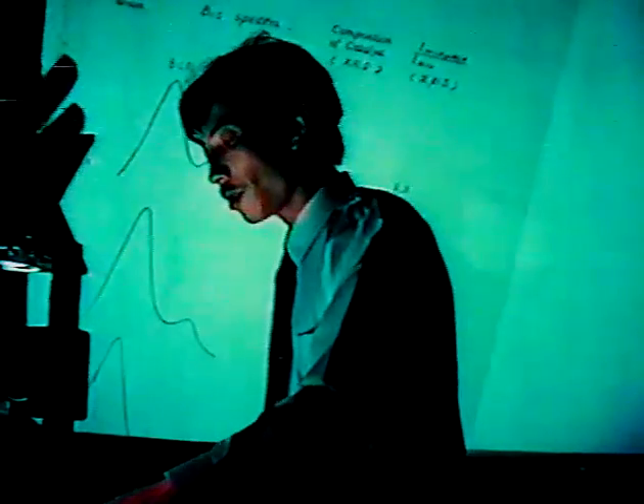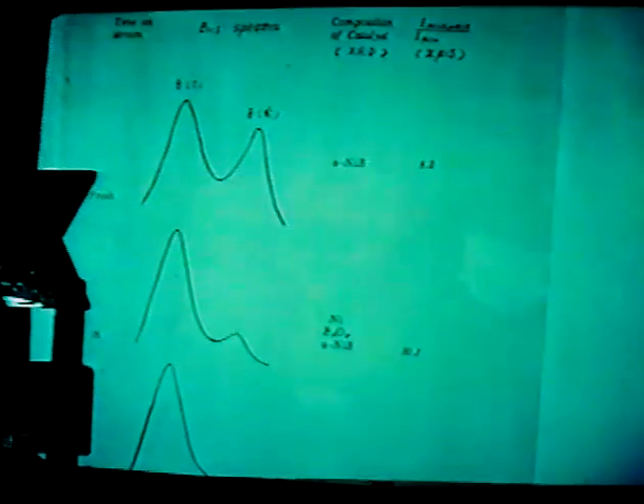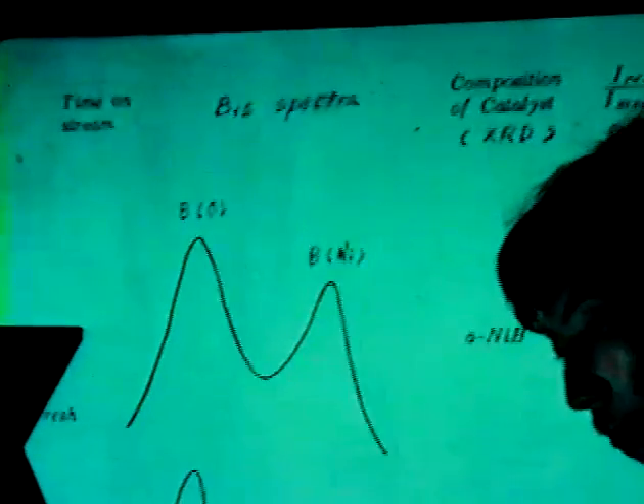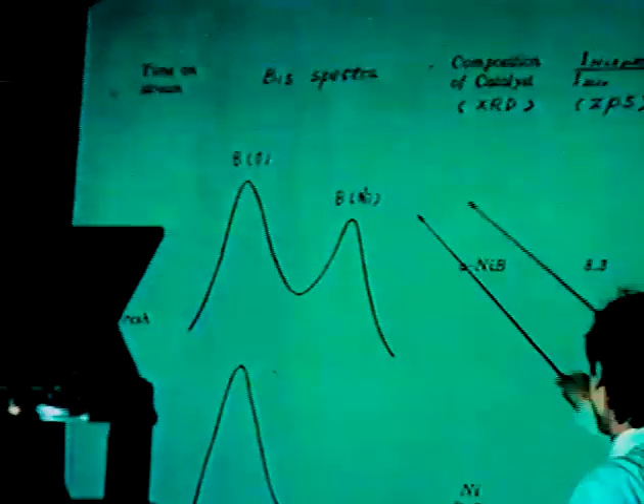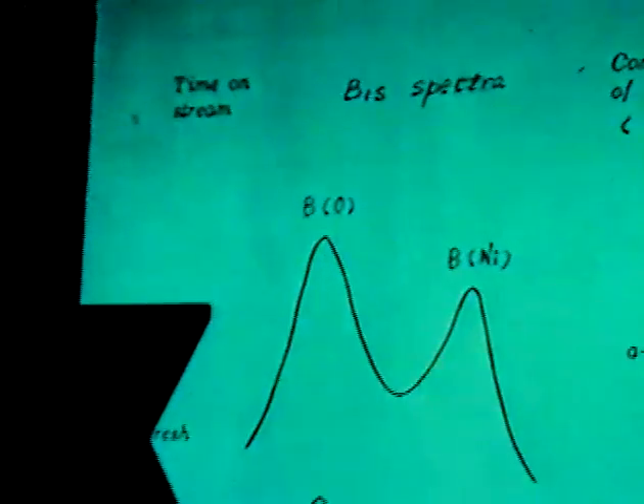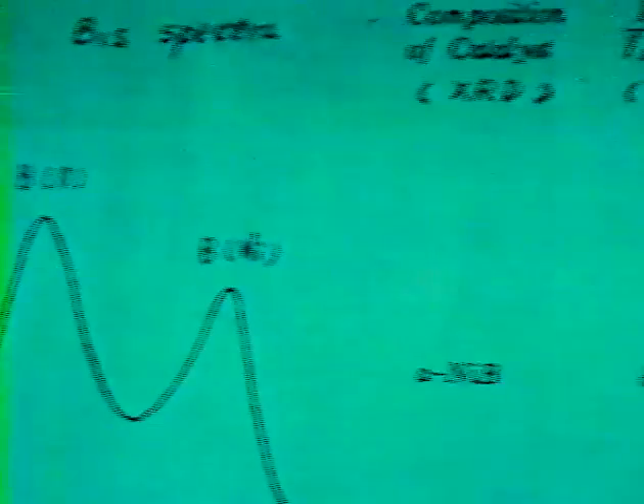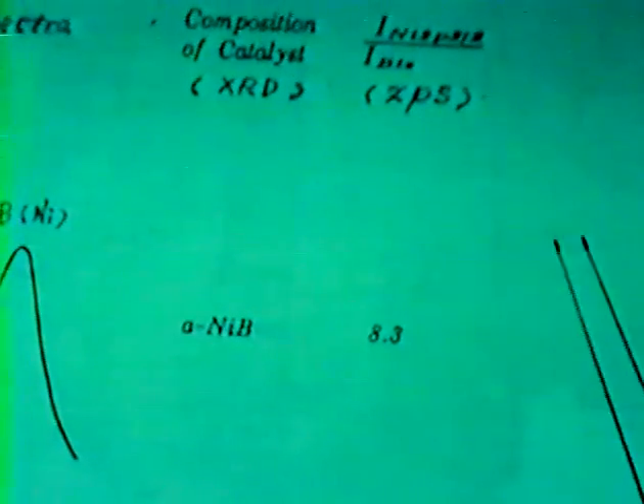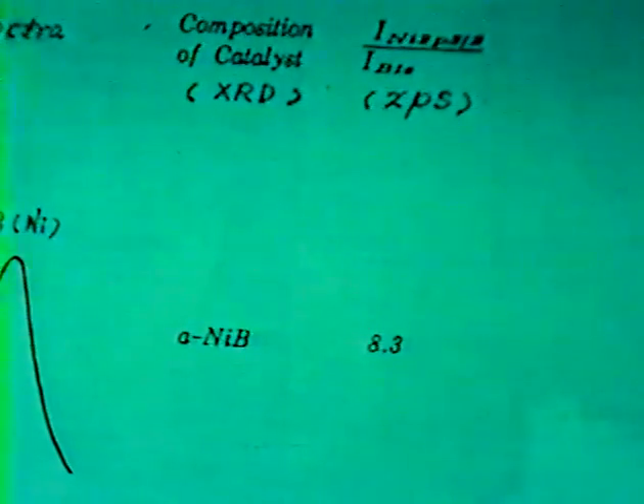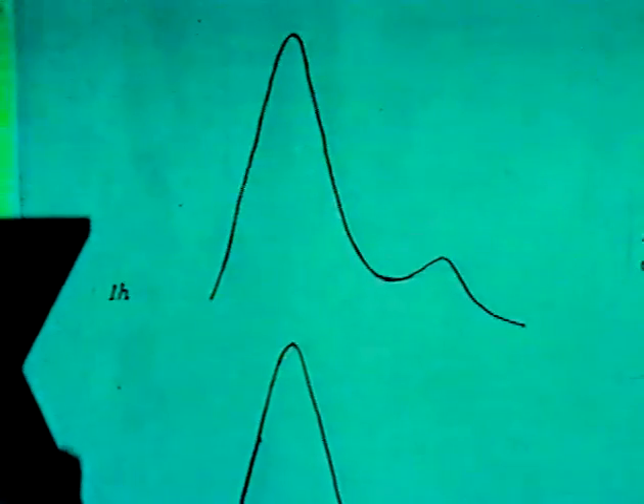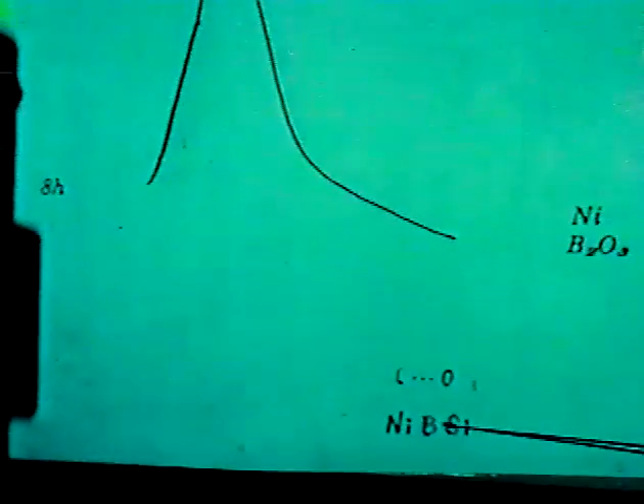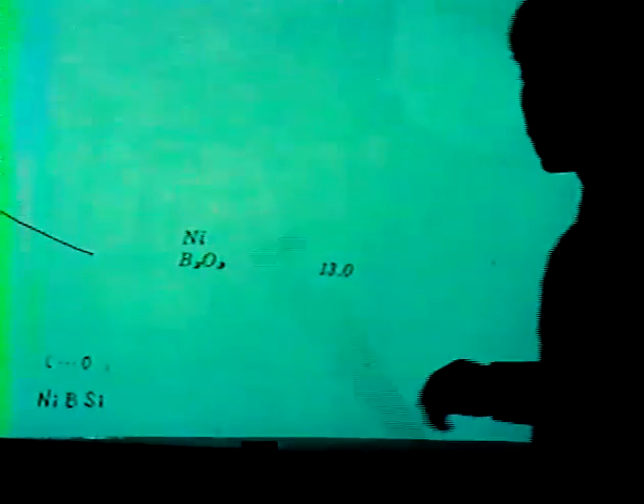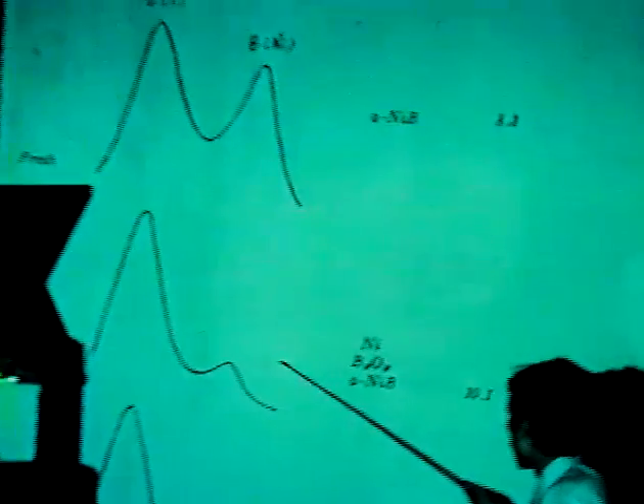Our XPS and XRD results evidence the changes in the structure and surface state of the catalyst. This is the boron XPS spectrum. This is the composition of the catalyst verified from XRD. This is the spectral intensity of nickel to boron. It has been reported in the literature that dissociation of carbon monoxide may result in the oxidation of boron. In our case, we also found part of the boron will oxidize after the reaction.